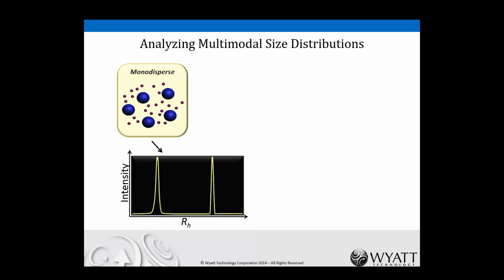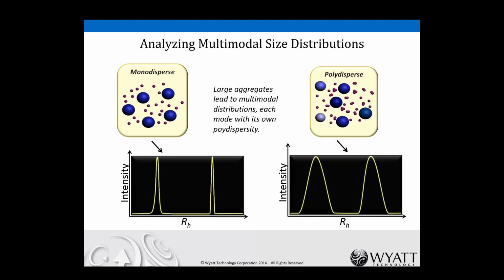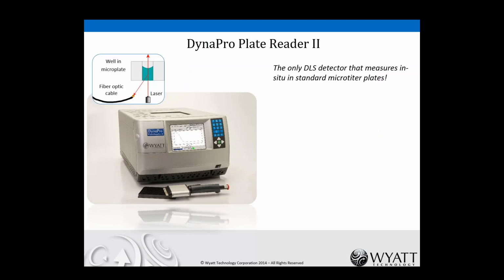If you have a multimodal size distribution, that means that you have in solution two size ranges, a smaller size and a larger size range, for instance, shown here in the cartoon, and those are actually resolved in the analysis. And if those modes are amongst themselves also polydisperse, so some aggregation perhaps on the smaller ones and the larger particles might have a distribution of sizes, again that leads to broadening, and so we can determine for both sets of particle sizes the average radius as well as the polydispersity. So you can get a lot of information with basically a very brief and non-invasive measurement.